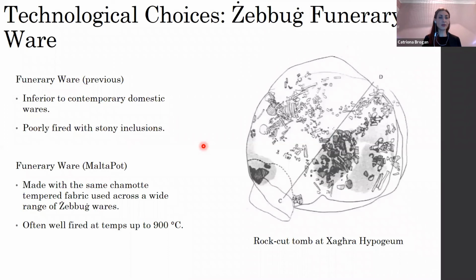But with our research, what we find is that the funerary ware seems to be made generally using this chamotte fabric, and it's often quite well fired up to 900 degrees. So from our sherds that we have, there's nothing really to suggest that it was that inferior. It seems to be using similar fabrics, and also can be well fired.